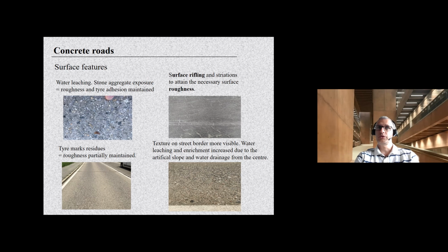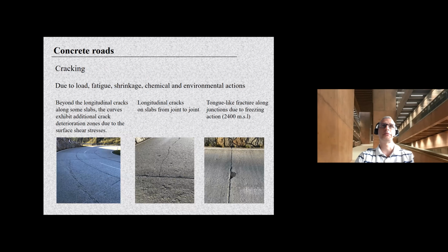And this is actually due to the water leaching and enrichments that is increased due to the artificial slope of the street that causes the water to flow on the side of the street to the water drainage. And during this flowing action, sometimes this fine graded cementitious material that holds together the stone aggregate is leached away, and the aggregate are exposed on the side of the slab.